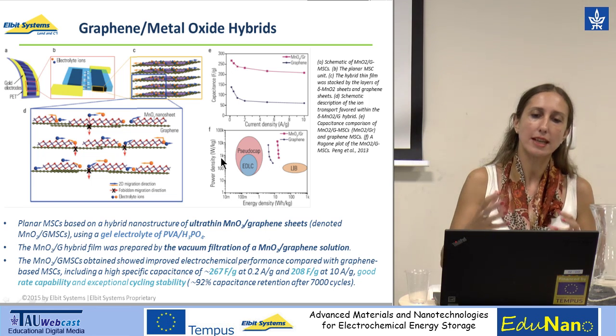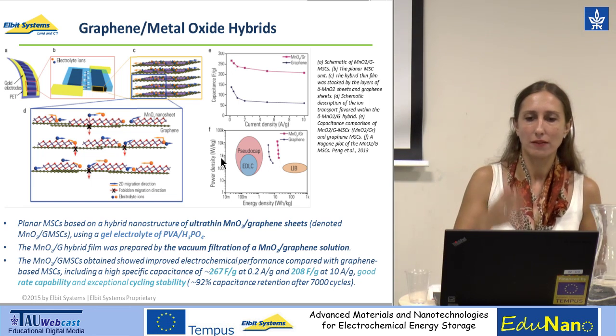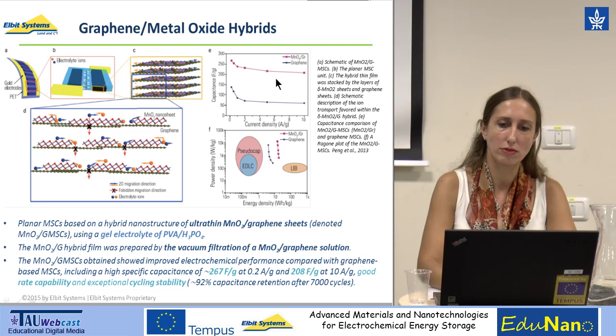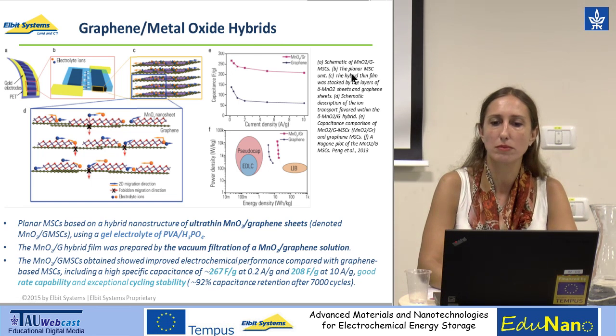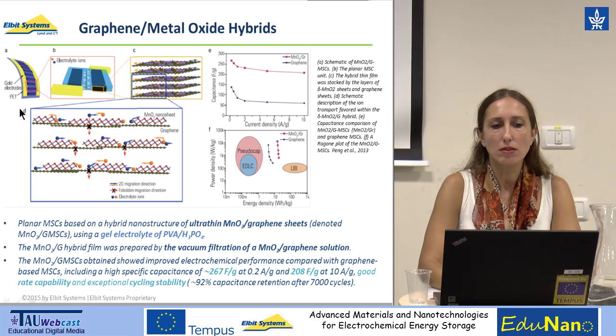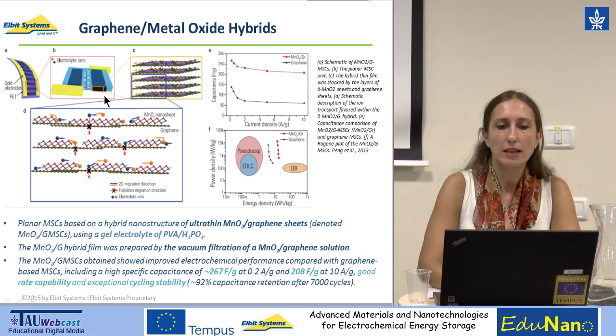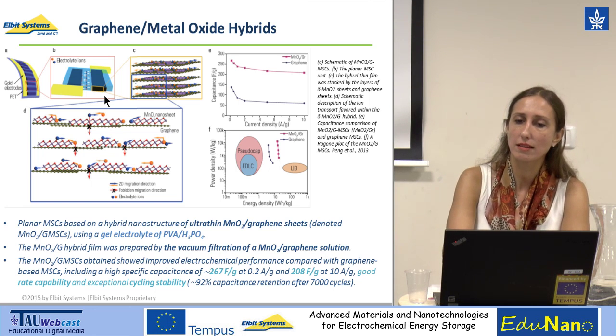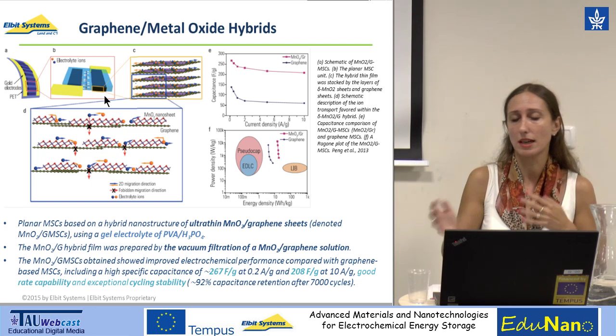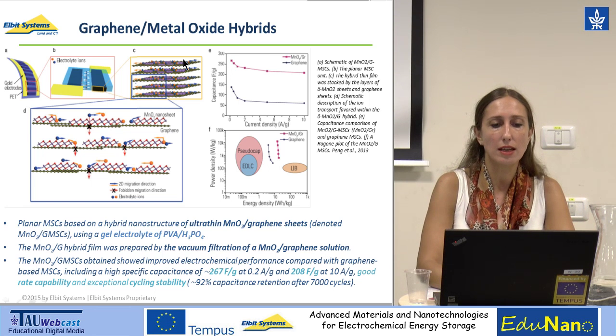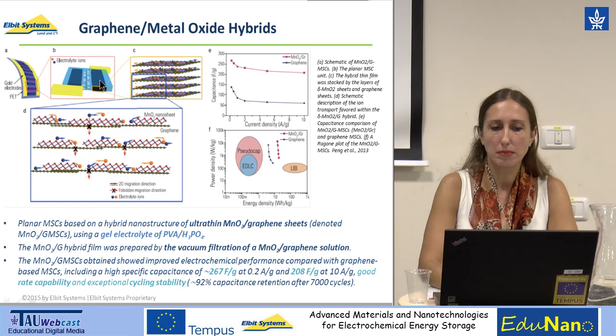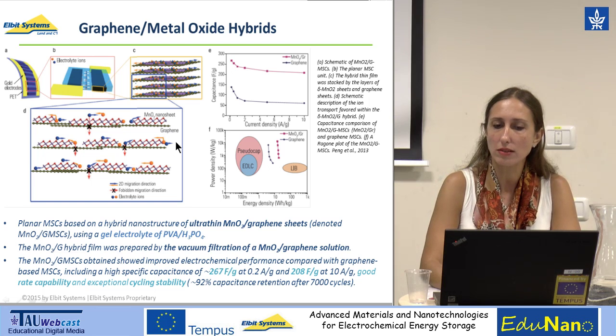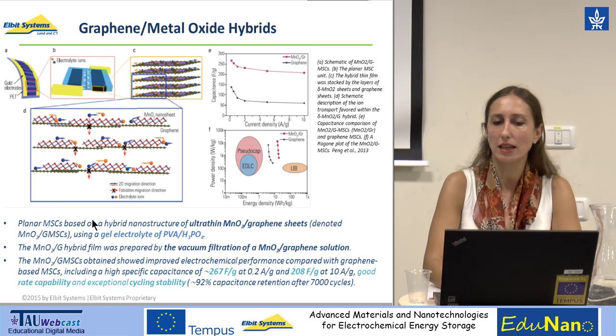What I would like to show here is exactly what we talk about now, but in a more schematic and visual way, in order to make it easier to understand the design of these hybrid graphene metal oxide electrodes. This is actually taken from research from 2013 by Peng et al. And what did they do? They used manganese oxide as a pseudocapacitance, the nano metal oxide active material, and graphene sheets. We are talking about planar graphene sheets or hybrid sheets based on a hybrid nanostructure of ultra-thin manganese dioxide and graphene sheets, denoted here as MnO2/GMSCs, using a gel electrolyte of PVA with phosphoric acid.